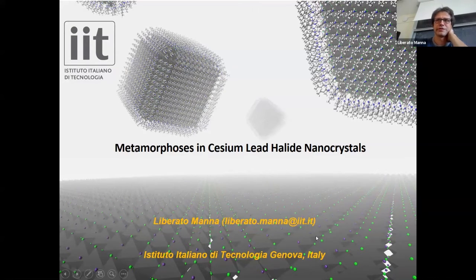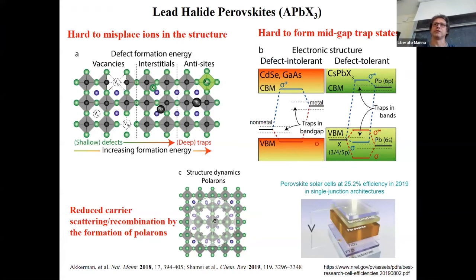Thank you for the nice invitation. I'm going to be talking about perovskite nanocrystals today. These are formed by networks of corner-sharing lead halide octahedra stabilized by large cations. In these materials, it's very hard to find defects. The only low-energy defects are vacancies.